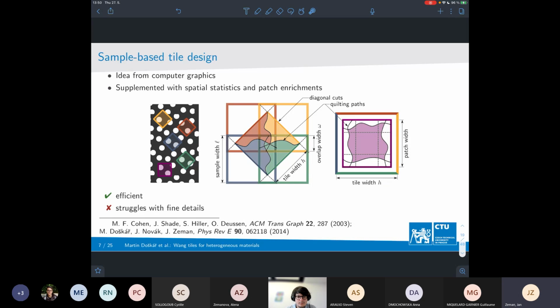Alternative number one is the so-called sample-based tile design, which is again an idea we borrowed from computer graphics. It works in a way that you take your original microstructure or picture, or texture if you wish, and depending on the number of codes you need, you select certain samples which are of the size of a given tile and are rotated by 45 degrees, as you may imagine. You take those samples, rotate them to the standard position, and allow them to overlap to a certain width. This is the first step.